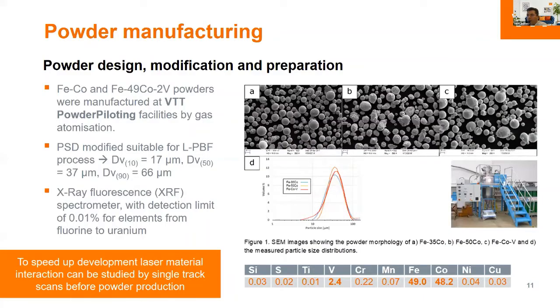This is one example about the powder manufacturing. Now, when I mentioned that we are focused on standardized alloys, we have focused on 3 different types of standardized alloys: 2 iron cobalt based soft magnetic materials, and also one iron cobalt vanadium containing soft magnetic alloy. We have produced those powders first at the VTT powder piloting facilities by gas atomization, and have studied what the properties of these powders are, what the particle size distribution is after the gas atomization process, and what the yield of the gas atomization process is.